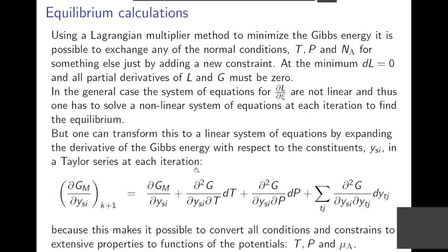So my professor teaching this, Mats Hillert at KTH, devised the method where you could expand your derivative of the Gibbs energy with respect to composition in a Taylor series. And from this Taylor series, you can extract a conversion, so all conditions actually depend on potentials: temperature, pressure, and the chemical potential for the elements. And that means you obtain a linear system of equations, which is much easier to solve. There are algorithms directly to handle it. But you need to calculate the second derivatives, which can be a bit cumbersome in some models.